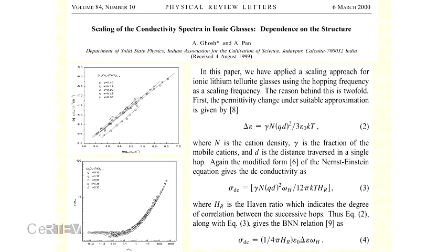When the structural unit is 4 coordinated, the structure is rigid. When the structural unit is 3 coordinated, so planar, the structure is floppy, they have told. And there is a transition. So my question was whether we can observe this with the scaling parameter. For one composition range there is one scaling, and for another composition range there is another scaling. The two scalings are not superposing; they are separated according to our model.